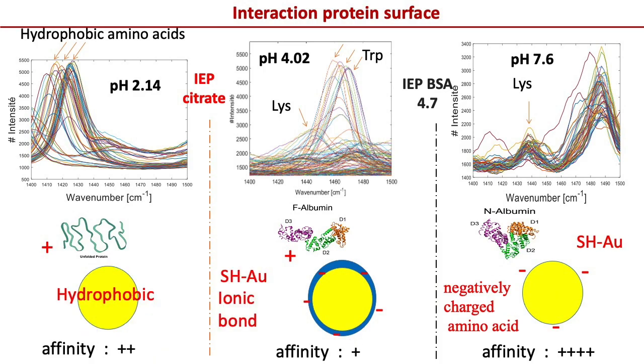The intermediate situation of the cigar shape remains the most complex. The protein structure is the most fluctuating, and from an absorption point of view, this is the least favorable situation. In fact, the citrate agent can act as an electrostatic bridge between the protein and the gold. The orientation of the protein is no longer fixed here. This supports the detection of aromatic amino acids in the protein such as tryptophan, whose Raman cross-section is the